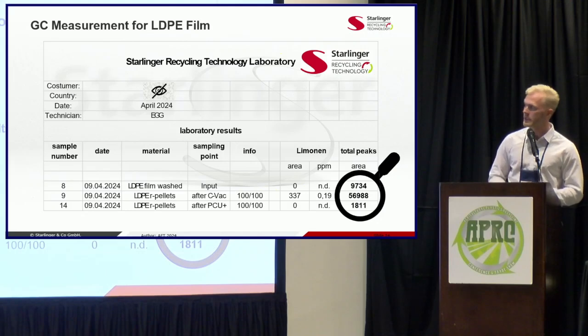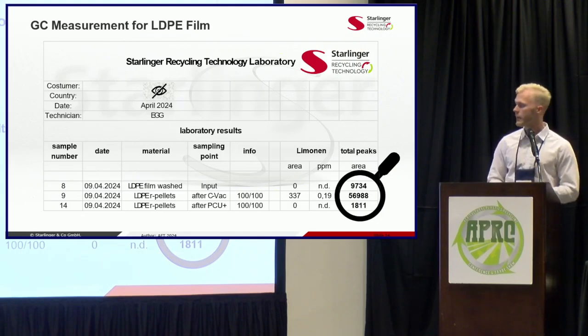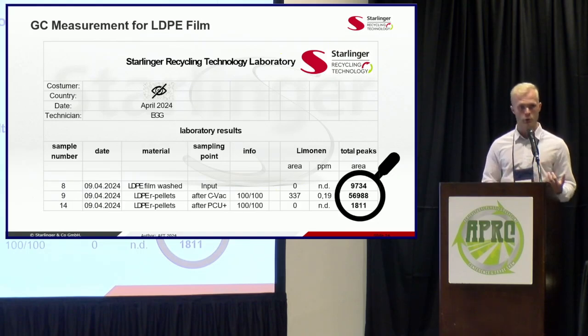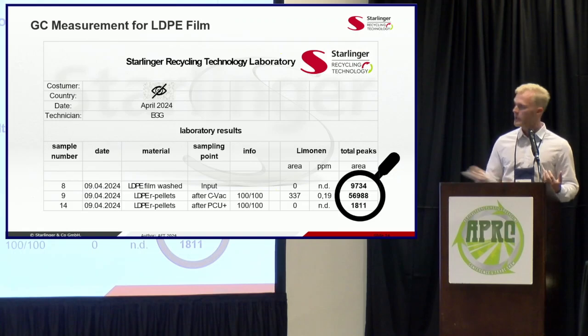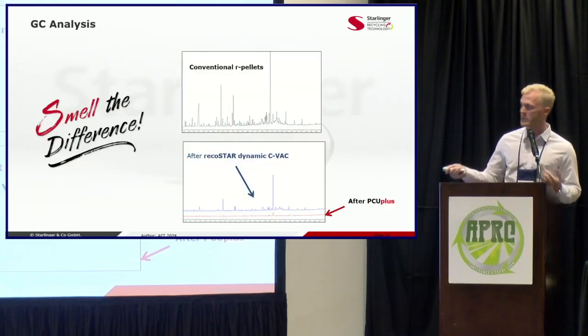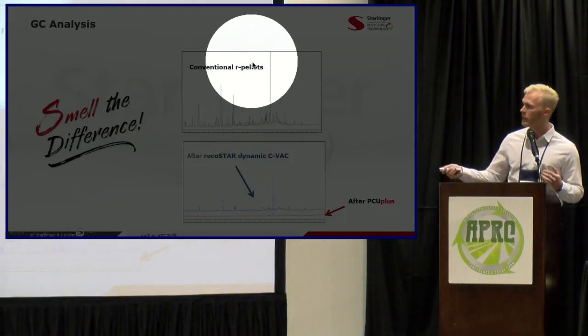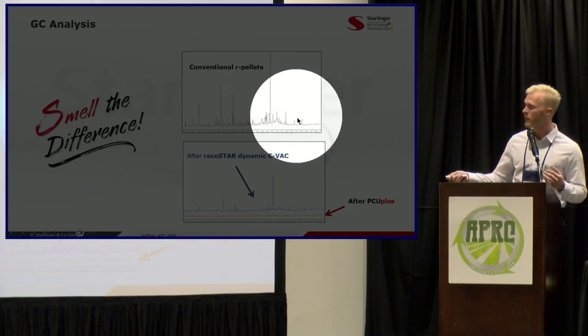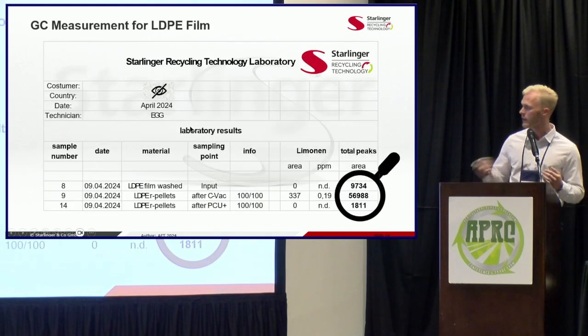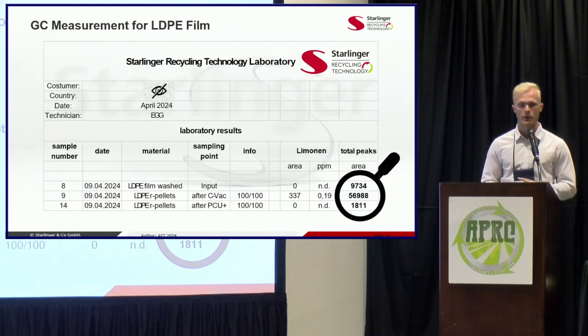And then this is an example of a GC measurement for low density film. And you can see that the total peaks in area are greatly reduced from the input to afterwards with the PCU+. So basically, with the GC screening, with that area measurement, you're taking the summation of all of the area under these peaks, and that number on the next slide is that resulting area. So that's a really good measurement and way to quantify.